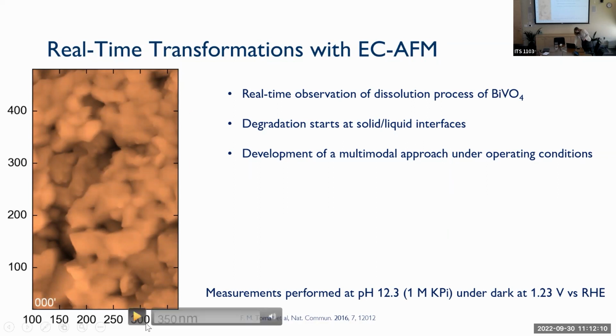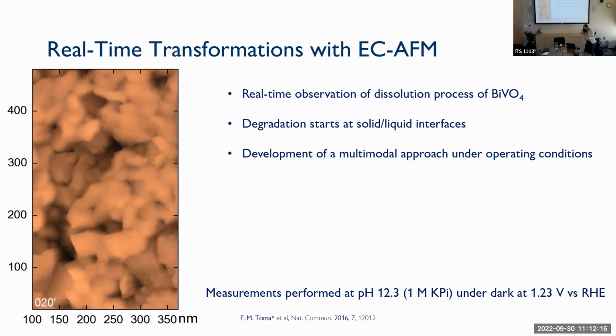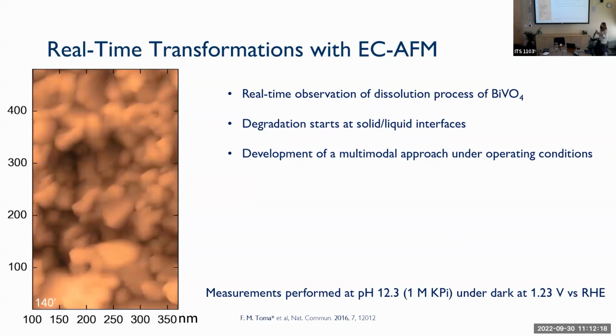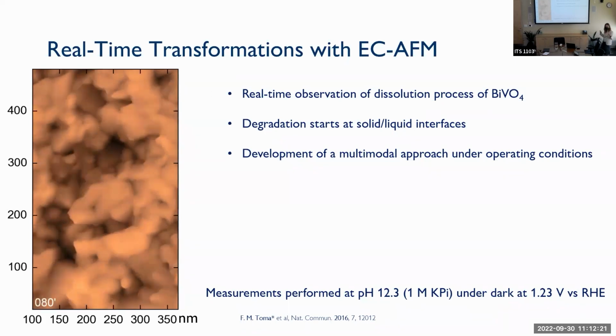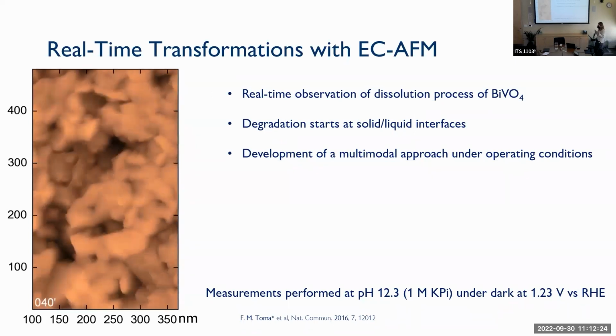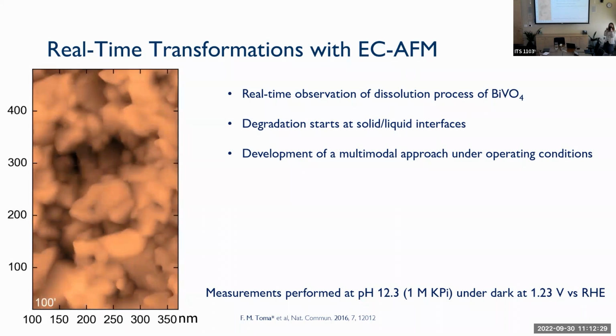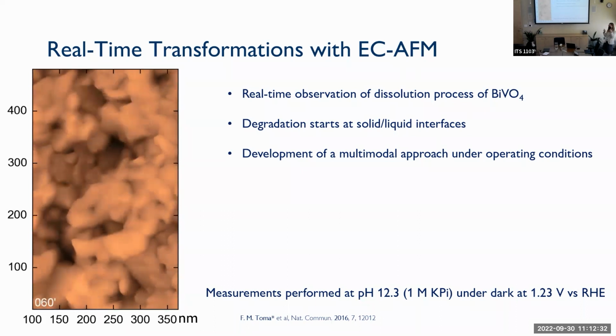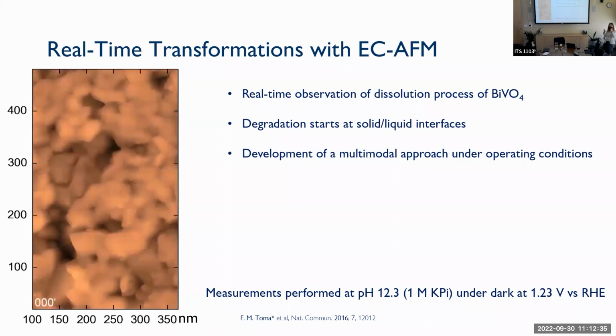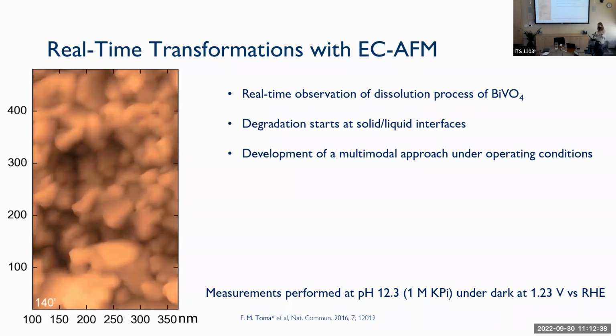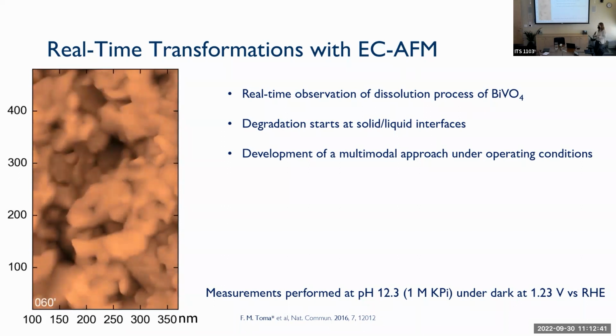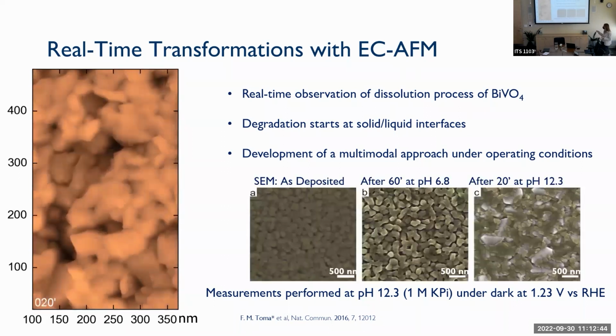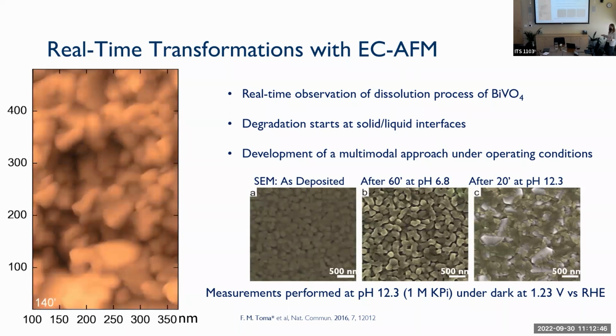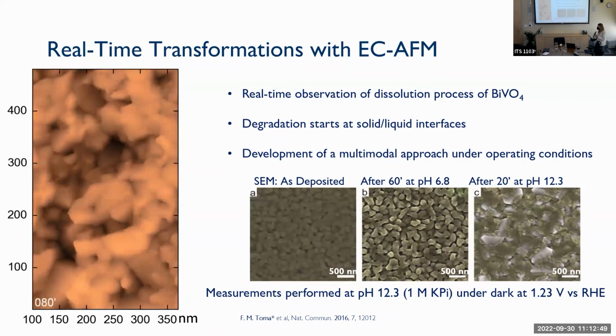So you can focus on anywhere on this video, but what you'll see is that the material is etching away. And with this technique, we were able to look at the real-time transformation of the material. And we were able, with statistical analysis, to understand that the corrosion process starts at the solid-liquid interface. So whenever the material is exposed to the liquid, that's where the degradation is going on, and then it just propagates to the rest of the material. And this is very much in line with the information that I showed you at the beginning, with scanning electron microscopy.